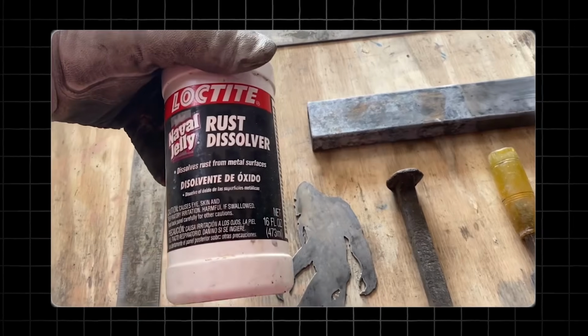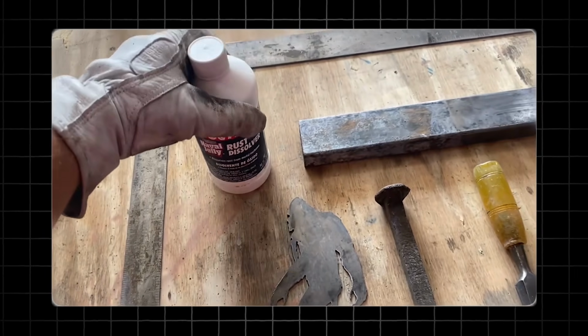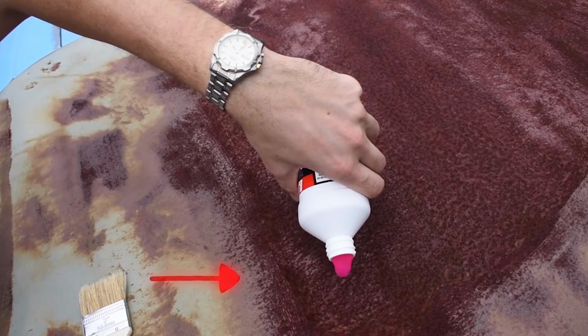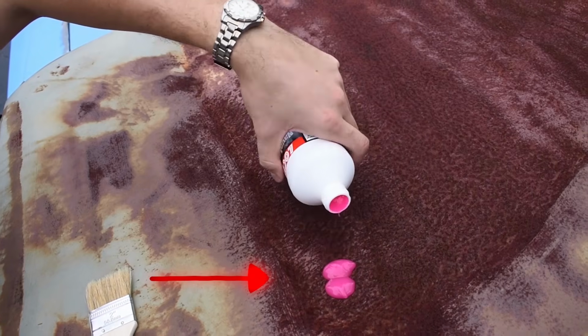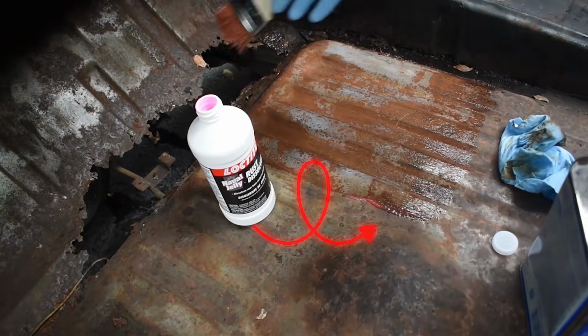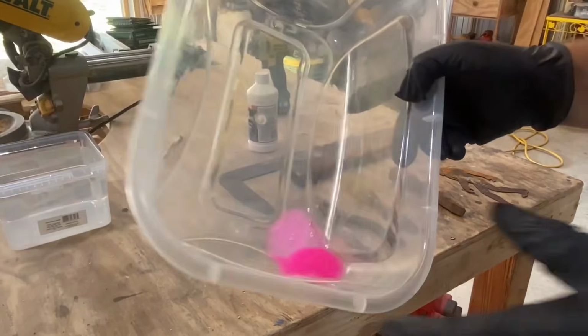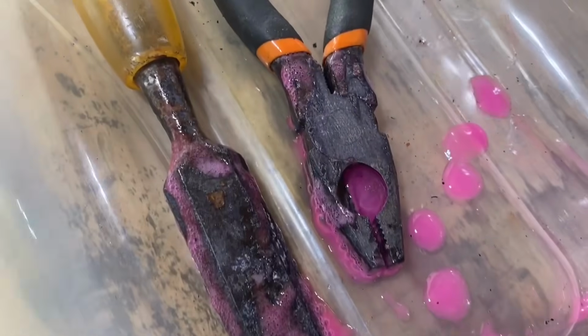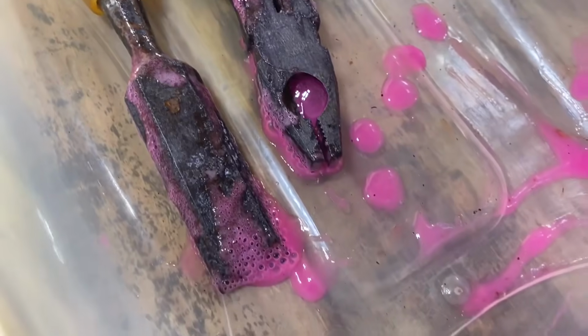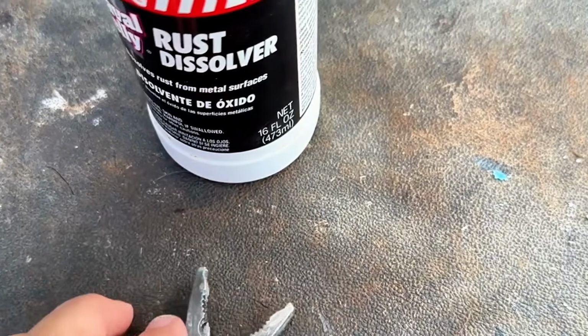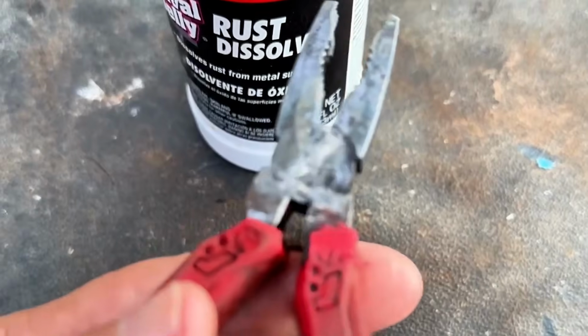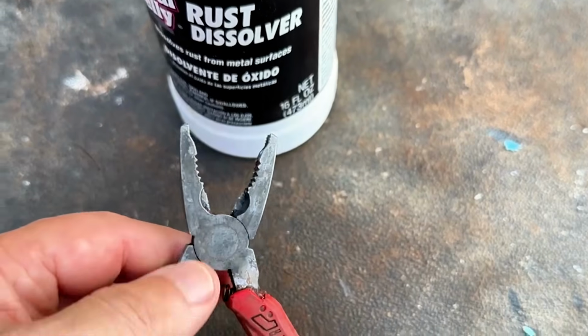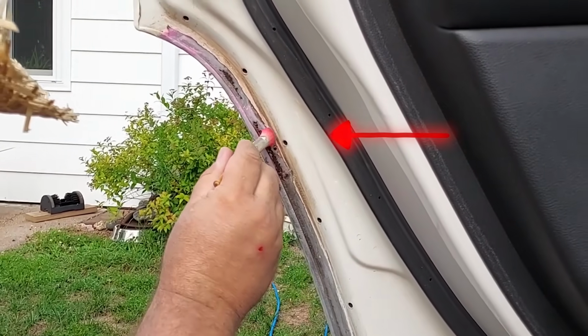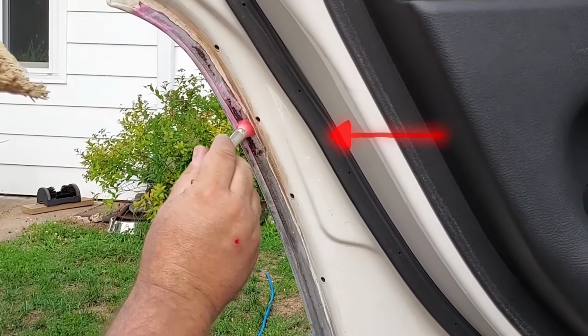It is one of the oldest commercially available rust treatment products in the consumer market. The gel formula uses phosphoric acid at a moderate concentration, thickened with a hydroxyethyl cellulose binder. The gel consistency is significantly thicker than Ospho and maintains contact with vertical surfaces for extended periods without running. In our testing, Naval Jelly maintained measurable contact time on vertical test panels for up to 20 minutes before the gel began drying and losing contact effectiveness.